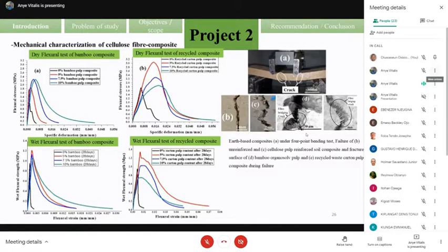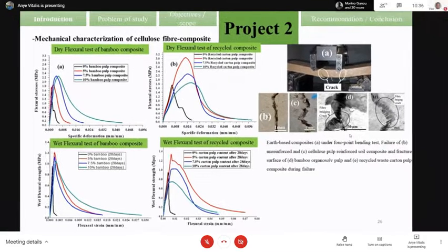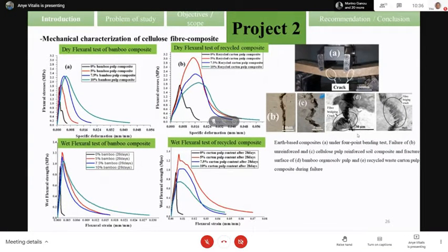Also, we study the mechanical behavior by using a four-point bending test on the composite in dry condition and wet condition. We realize that in both wet and dry testing conditions, the composite reinforced with fiber was improving on the mechanical property. And also, there was a transition from brittle to pseudo-ductile material by using fibers.